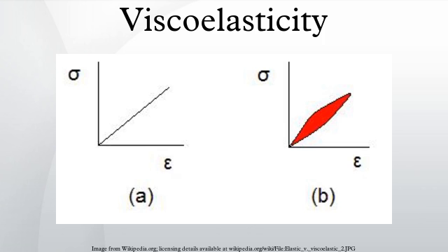First, fit the creep data with a model that has closed-form solutions in both compliance and relaxation. For example, the Maxwell model in or the standard solid model in. Once the parameters of the creep model are known, produce relaxation pseudo-data with the conjugate relaxation model for the same times of the original data. Finally, fit the pseudo-data with the Prony series.